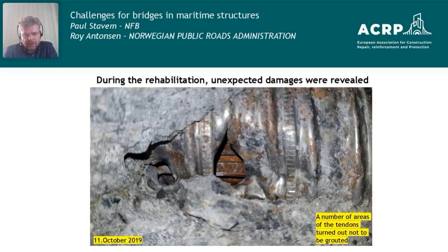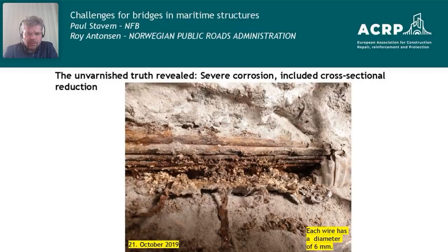But as we went along in the project, we found more and more of these voids, and we had to change our plans. So it was no longer like we considered. We had to stop these plans we had about installing cathodic protection, and rather think about strengthening the bridge. But the case is that we found more and more severe damages, and as you can see here, this is severe corrosion, gravrust as we call it in Norway.